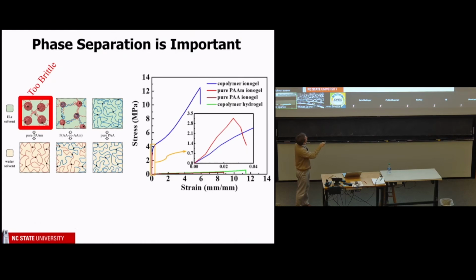And if you look at the stress-strain behavior, that's this red data, and it's very brittle. So it's really hard to break, but then it doesn't go to large strains. If you look at the baby diaper material or any of these, they're all very well solvated with the solvent. And you see that they stretch to very, very far strains because those spaghetti noodle molecules can stretch out. They can be elongated without any issue, but they don't require much stress to break.